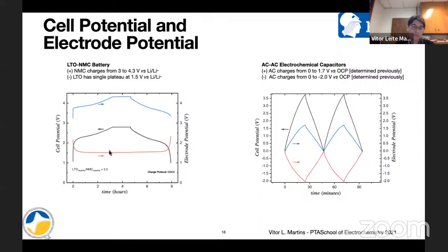And that is done by balancing the capacity of each electrode. So in this case here, I have 2.5 times more capacity in the negative electrode than in the positive electrode. And it's basically the same here. We need to balance the charge of those two electrodes. The positive electrode can charge up to 1.7 volts, and the negative electrode in the capacitor here can charge down to -2 volts. And the balance of charge of each of these electrodes will tell me where the cell potential will be cut off, all right?